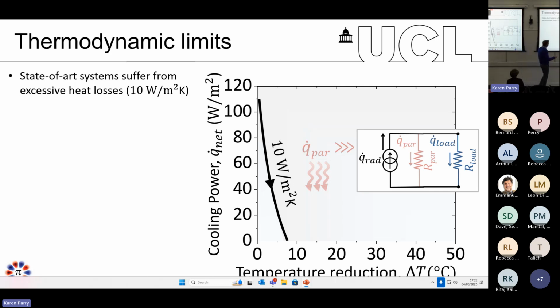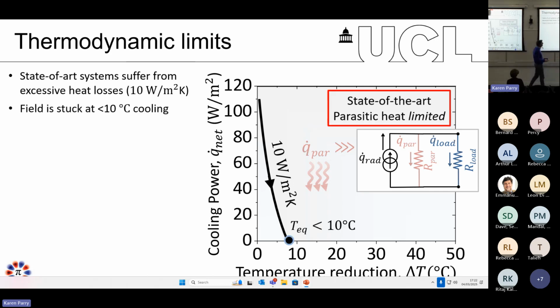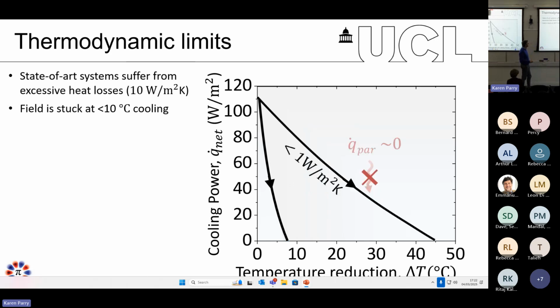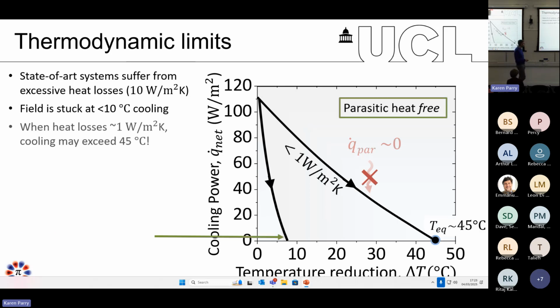But what happens if this is reduced, say, by an order of magnitude down to, say, 1 watt per meter square Kelvin? This is, by the way, absolutely possible with today's technologies. The double glazed window has that type of thermal insulation. So now suddenly you have a dramatic change in the cooling power, and the system is able to equilibrate at 45 to 50 degrees below ambient. We're talking about completely passive refrigeration, deep refrigeration. Okay?